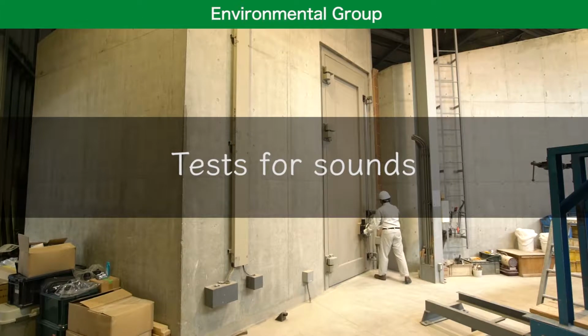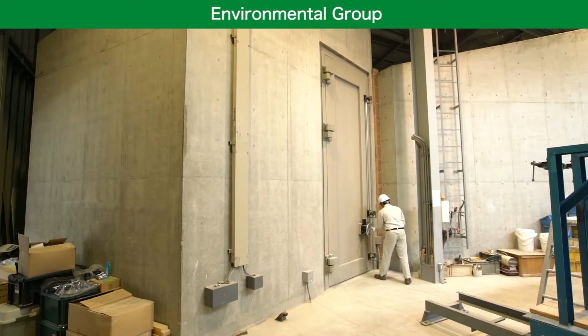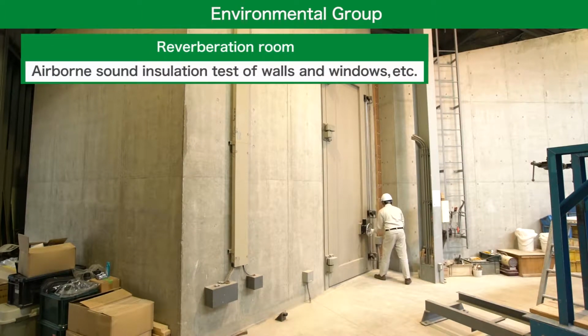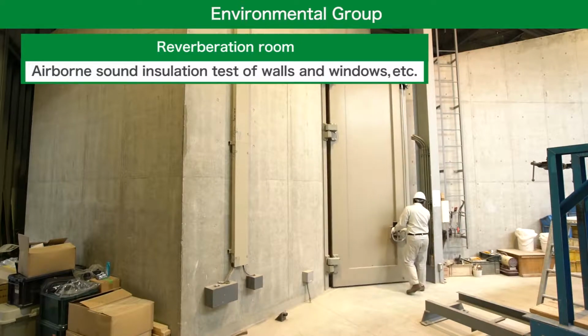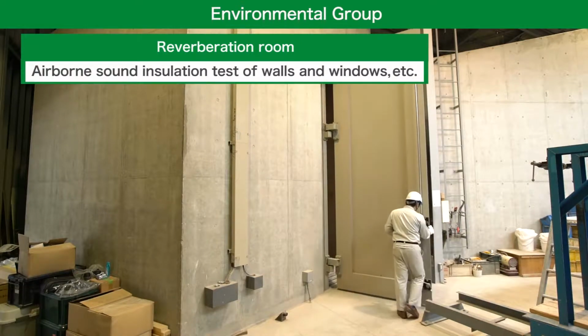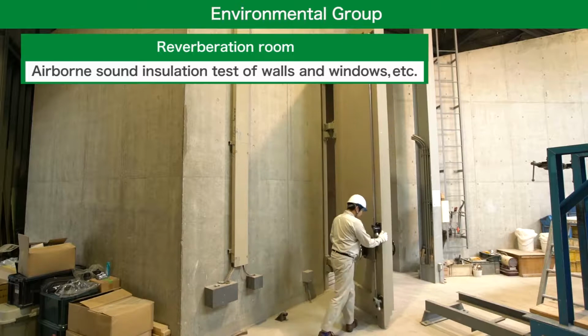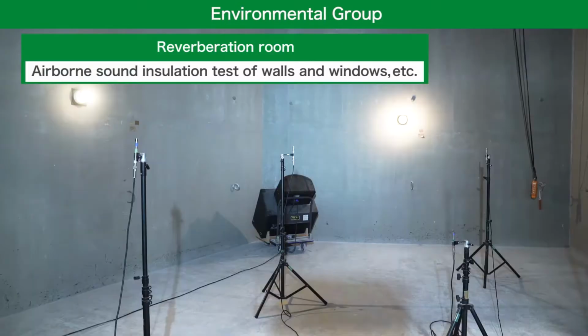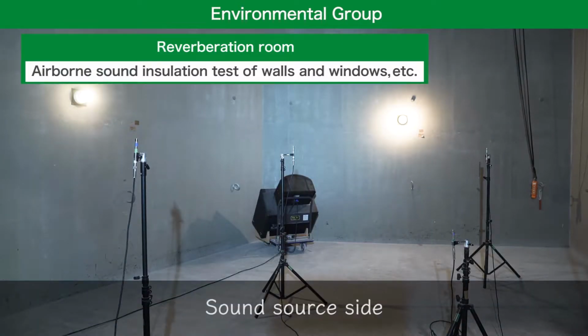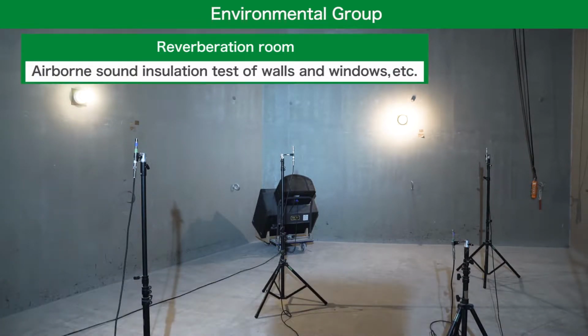Now let us introduce tests for sound. A performance test of sound transmission loss is conducted by using 2 adjacent reverberation rooms. Sound is generated by a speaker in the sound source room so that sound emanates from various angles toward the specimen. The specimen vibrates from incidental sound, and the sound is radiated to the sound receiving room to the rear. Then the transmittance of the sound is measured based on the energy density of the sound in the sound source room and the sound receiving room at that time.